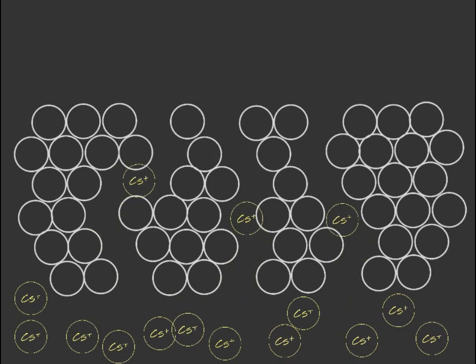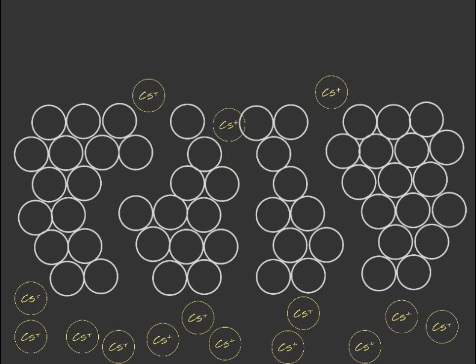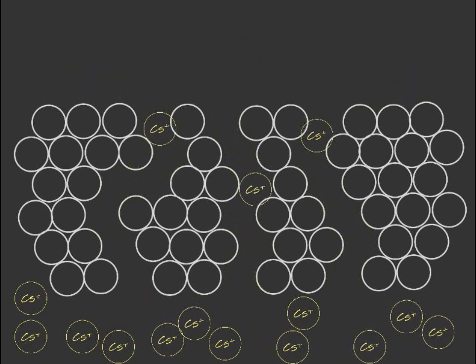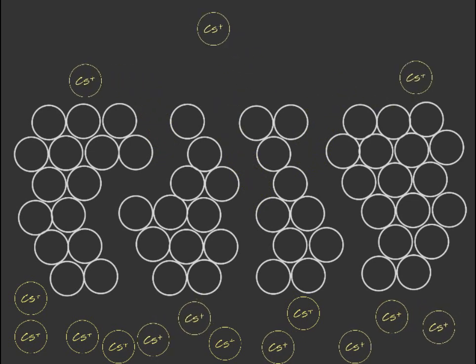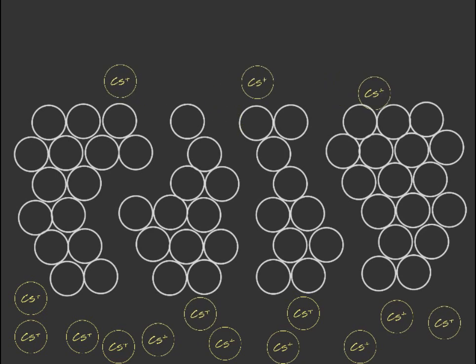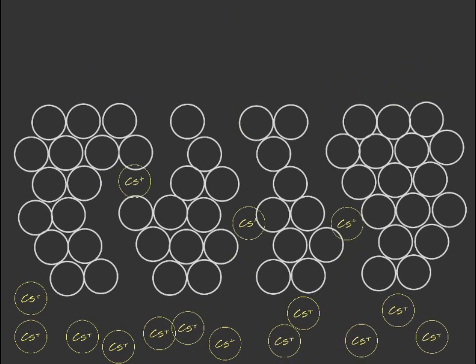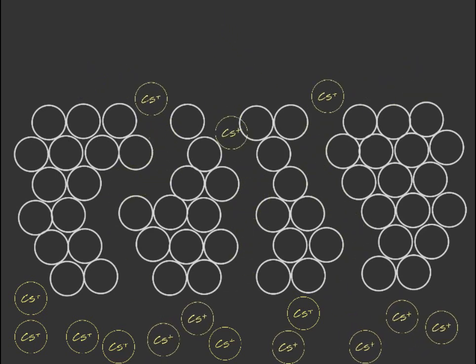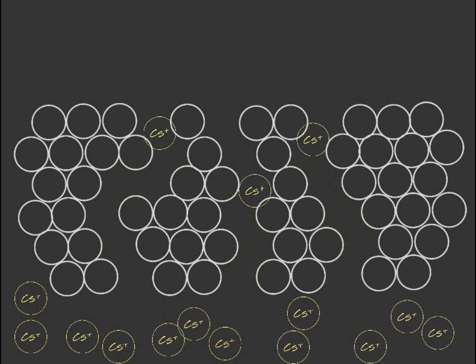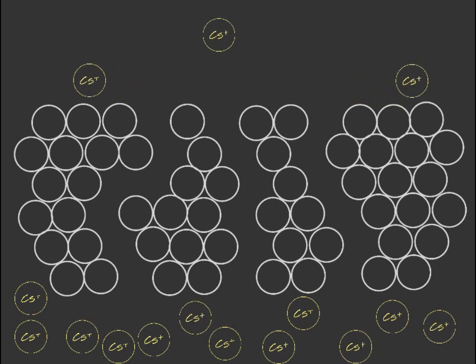So how do these cathodes work? Well, inside the photocathode is a reservoir of cesium atoms that flow through the pores in the tungsten onto the surface when heated. The cesium then diffuses across the surface and will evaporate off over time. This is caused by the same heating on the reservoir itself. It provides enough thermal energy for the cesium atoms to break free of their attraction to the photocathode's surface.